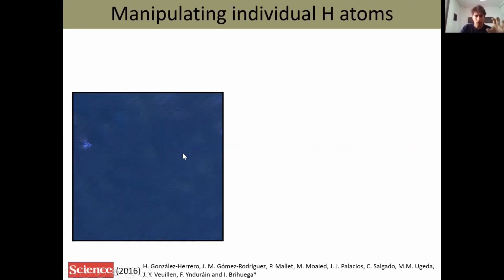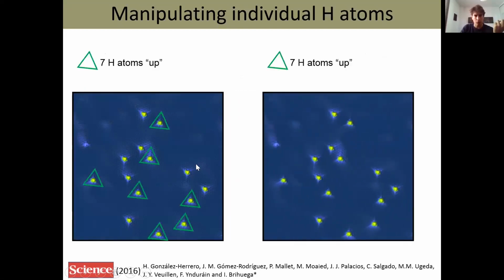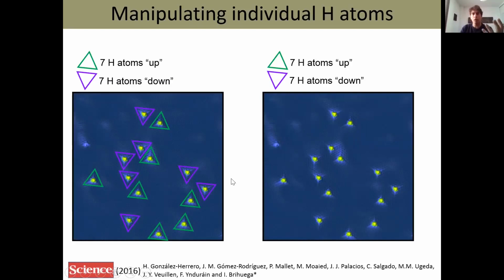Instead of this, I would like to show you how we can manipulate those hydrogen atoms. So we can use STM to manipulate hydrogen atoms, which will be useful in the next part of the talk. Here we see a pristine graphene layer, no hydrogen atoms, and now we deposit 14 hydrogen atoms with the tip. And if we take a close look at those hydrogen atoms, 7 of them are pointing up, so they are in one sublattice, and the other 7 are pointing down. And from what we learned of the magnetic couplings, since we have 7 in one sublattice and 7 in the other sublattice, we know that the magnetic moment induced here should be 0 or close to 0.